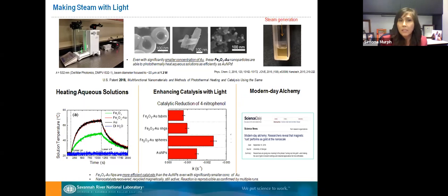And of course, we implemented this for a model catalytic reaction of 4-nitrophenol. If you take a look here, we can see that the iron oxide gold spheres were better catalysts for this reaction than the other shapes. And again, when we compare with the gold, just by replacing some of the gold material with iron oxide, it was a better catalyst. We published this in a couple of journals, and we have a patent on this. We also got a little bit of PR on this. If you search modern day alchemy, we made the iron oxide and turned it into gold.